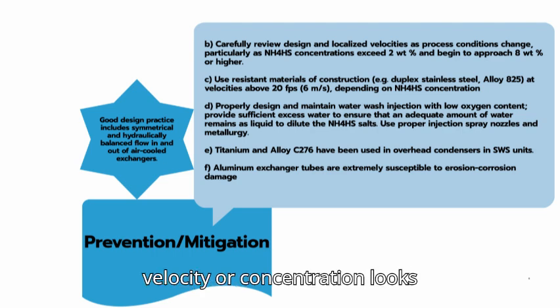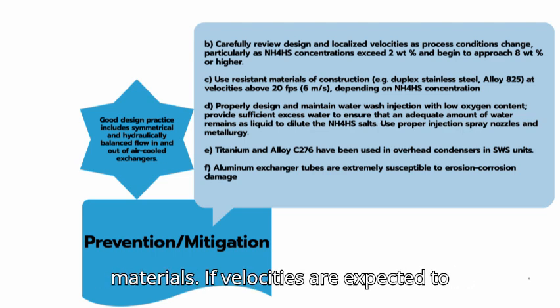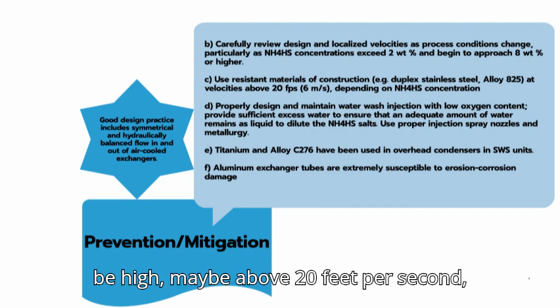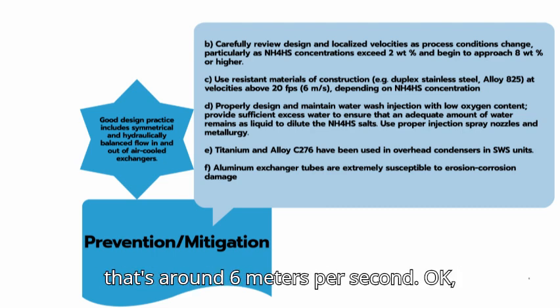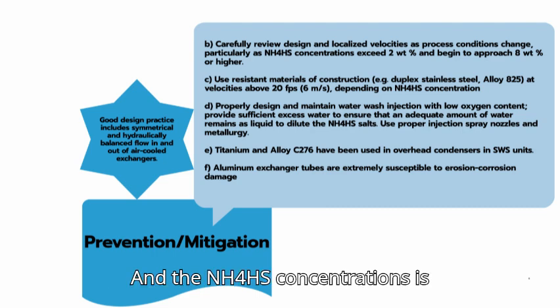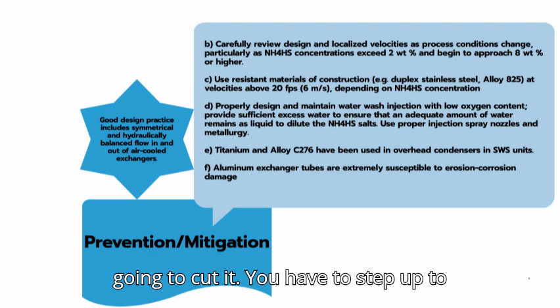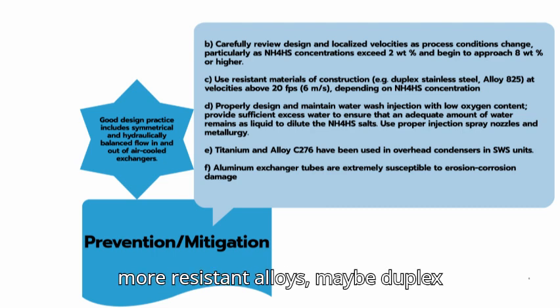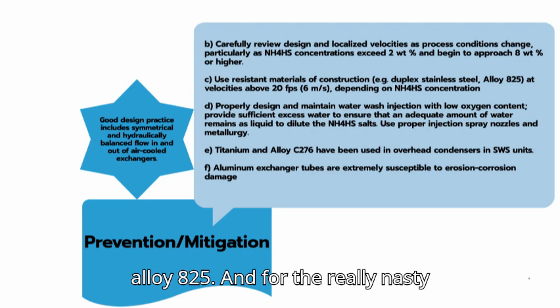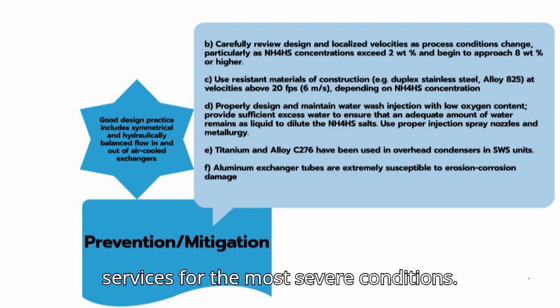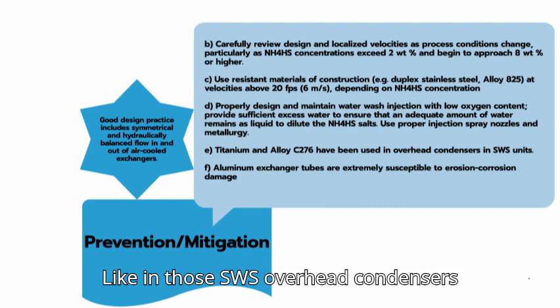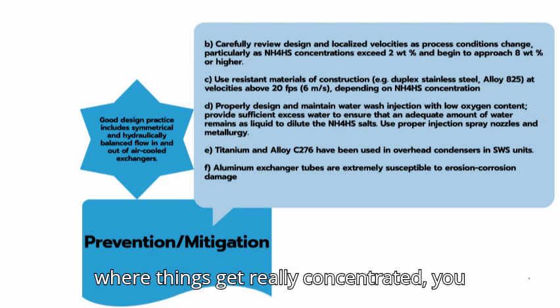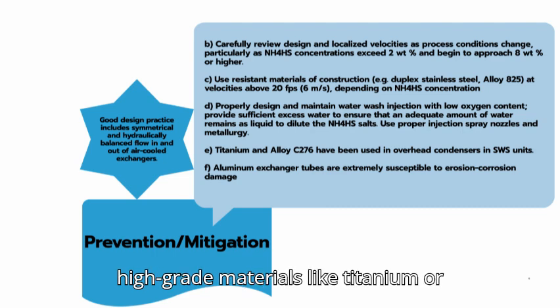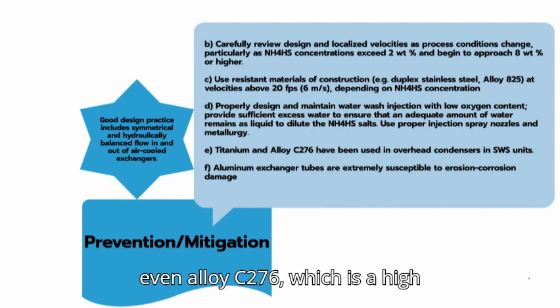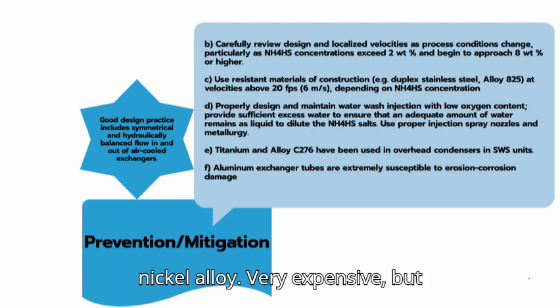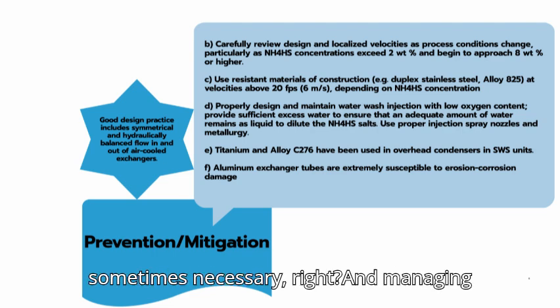And if the velocity or concentration looks problematic, then you have to upgrade the materials. If velocities are expected to be high, maybe above 20 feet per second, that's around 6 meters per second, and the NH4HS concentration is significant, carbon steel is just not going to cut it. You have to step up to more resistant alloys. Maybe duplex stainless steel, maybe something like Alloy 825. And for the really nasty services? For the most severe conditions, like in those SWS overhead condensers where things get really concentrated, you might see engineers specifying very high-grade materials like titanium or even alloy C276, which is a high nickel alloy. Very expensive, but sometimes necessary.